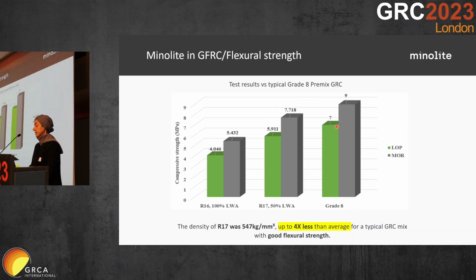The last one is the typical GRC mix, and this one is when 50% Minolite was used. You see that, of course, the flexural strength is a bit lower, and when you're using R16, the flexural strength is even lower. But we should consider that the density of R17 is 4 times less than the density of the typical GRC mix, which is very significant. The compressive strength is lower, but not very significant.